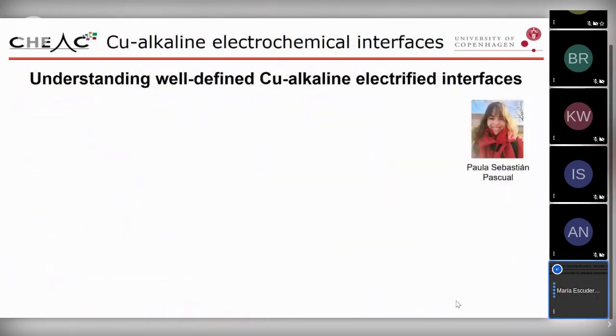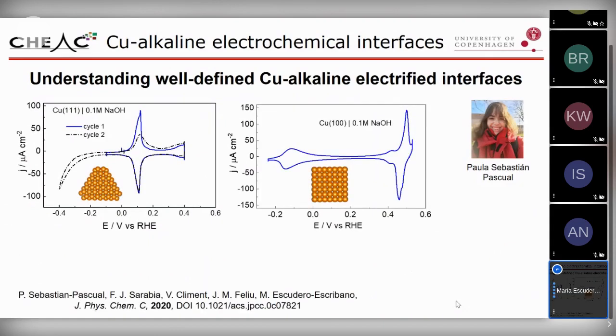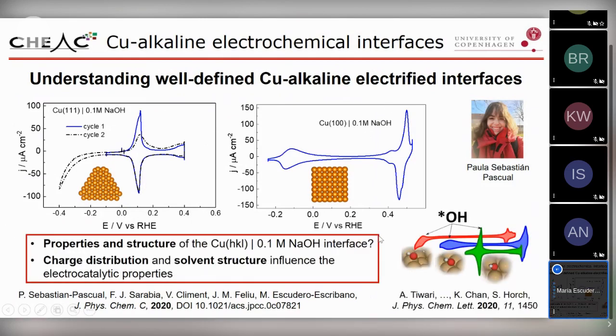And all the work I'm going to present has been done by Paula Sebastian, who is a postdoc in my group. So first, starting with alkaline, Paula investigated both copper 111 and copper 100 in sodium hydroxide. And then here we can see both the effect of the cycling potential range and, from the CVs, the fact that everything is very well ordered. And we can see the characteristic features, both in copper 111 and copper 100, of the adsorption of OH.